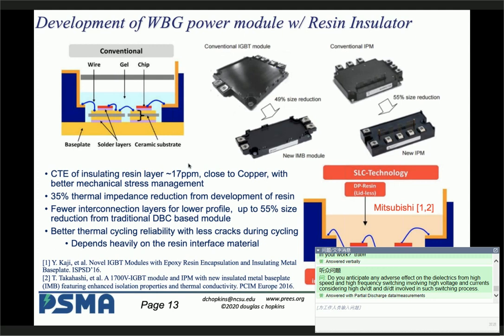And so, all of that dV/dt and dI/dt. It's one thing to have the dV/dt going from conductor through dielectric to conductor. Then the question is that capacitive discharge current that you're looking at through that conductor. That's the whole idea, right? It's a capacitor, right? And how much can you get through that? And so, what are you doing to that dielectric as you start to put such high stress, volts per micron or volts per nanometer, across the molecular structures within these dielectrics. It all gets back to what does your PD testing tell you about the purity and about the void rates, and then you can extrapolate into what your dV/dt across the dielectric can be limited to.